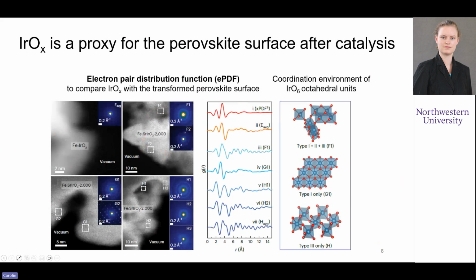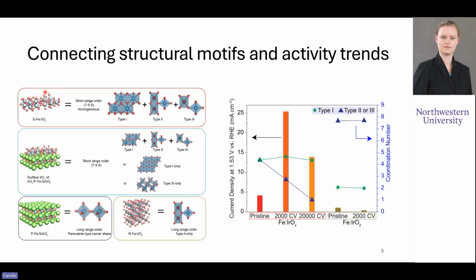Now, let's take a look at how those structural motifs dictate the activity of our material. Just as a summary, we have our iridium oxide that has homogeneous short-range order and these three types of iridium-O6 octahedral units, versus the surface of our perovskite, which also has short-range order on the same length scale. And some areas show these three types of connections, versus there are others that show type 1 or type 3 only.